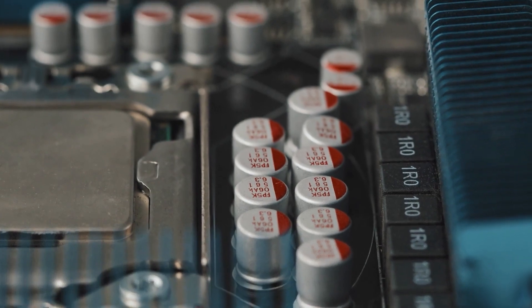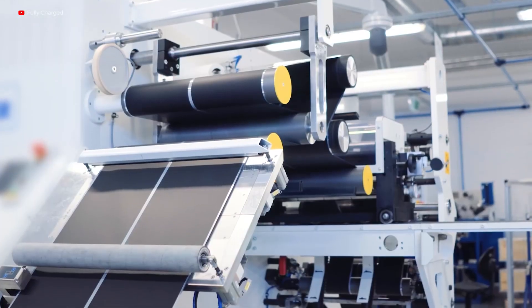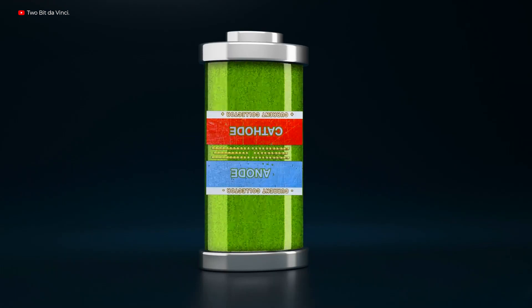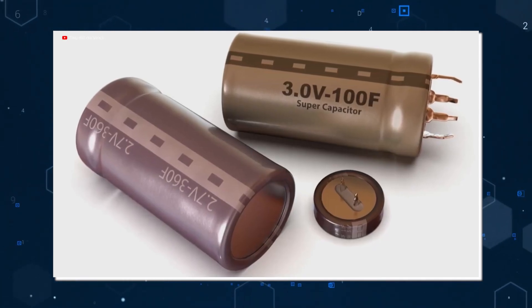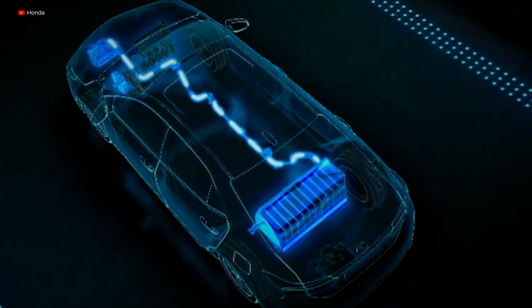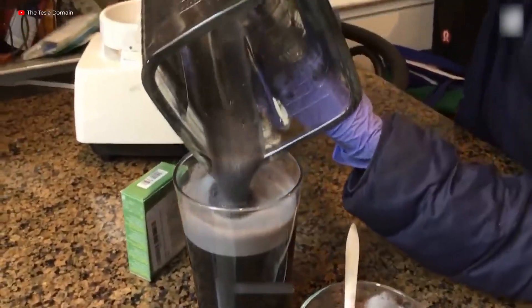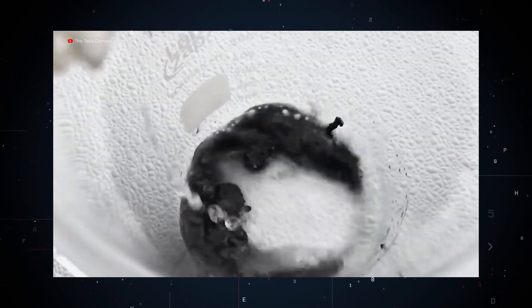To date, their lack of energy density was the one problem with supercapacitors, so Fischer's team developed a powerful and sustainable graphene hybrid material for supercapacitors. Serving as the positive electrode in the energy storage device, the researchers are combining it with a proven negative electrode based on carbon and titanium. The new energy storage device performs much better than most other supercapacitors, at a power density of 16 kilowatts per kilogram, and attains an energy density of up to 73 watt hours per kilogram, roughly equivalent to the energy density of a nickel metal hydride battery. The secret of the new supercapacitor is the combination of different materials, hence being referred to as asymmetrical by chemists.